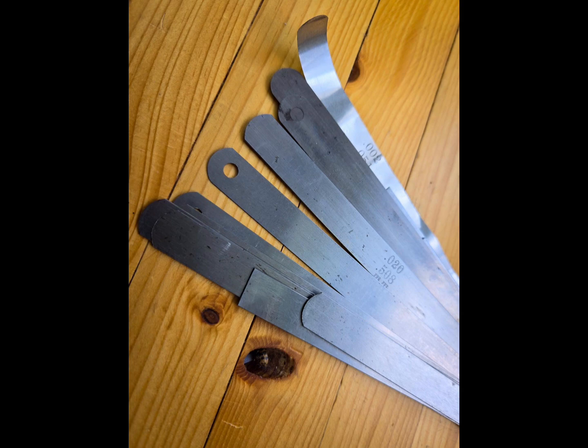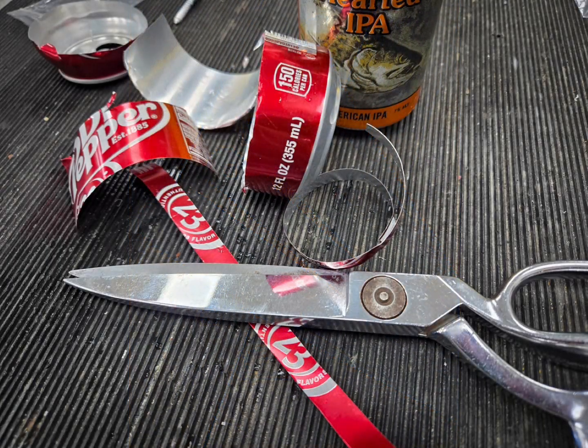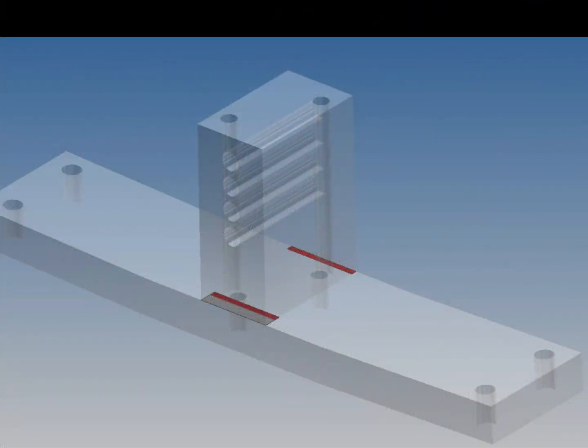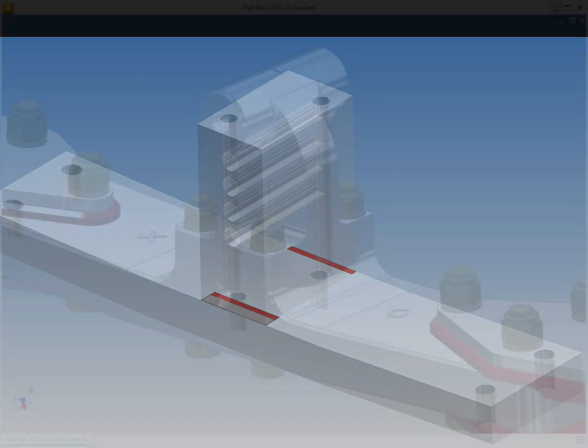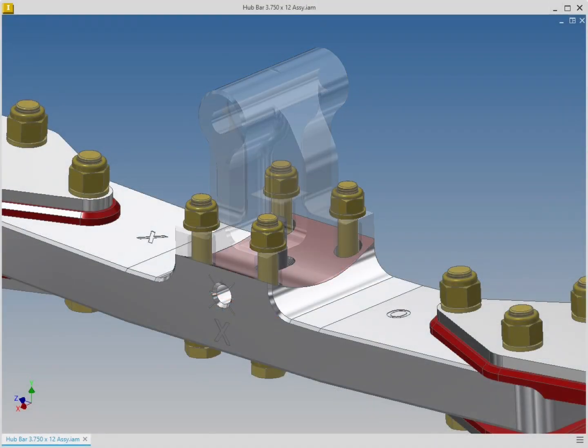On other systems, you'll have to adjust the tracking by using shims between the hub bar and the teeter block. Although this works, it's certainly not an elegant solution. Just for reference, 1/8 of a turn of the set screw would equate to adding a 3,000th shim on other brands. A shimmed assembly will also result in the force being spread across just two thin lines of contact between the teeter block and hub bar, whereas the razor blade system retains full surface contact between these components regardless of the pitch setting.